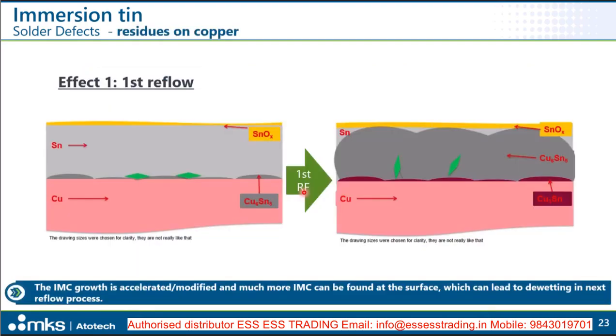A bit more looking into what's going on there. For example, if you have any residues on copper which are not removed before the tin plating process, right after the tin plating they are sitting at the interface between the tin and the copper. And then what's happening during the first reflow cycle is that they can move with the IMC growth into the tin layer and may even affect the formation of the IMC growth, or may even trigger the IMC growth in these areas.